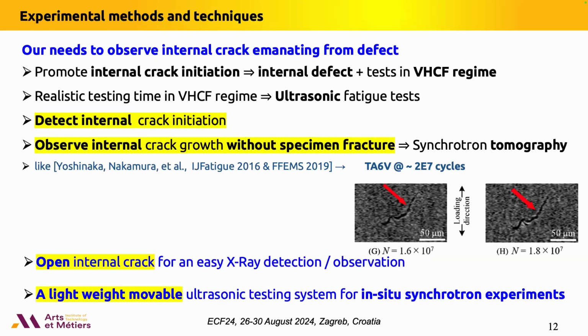And to do the test in realistic conditions, because the synchrotron time shift allows you typically a few days, sometimes 2 or 5 days maximum, we need a quick test. So we do the test at ultrasonic frequency. And to detect the crack initiation during the ultrasonic fatigue testing, it is necessary to use an ultrasonic system that is able to detect automatically the crack initiation. So I will show you on the next slide the principle of the testing machine. The testing machine needs to be mounted on a synchrotron beamline. So we need a light, compact ultrasonic testing system.